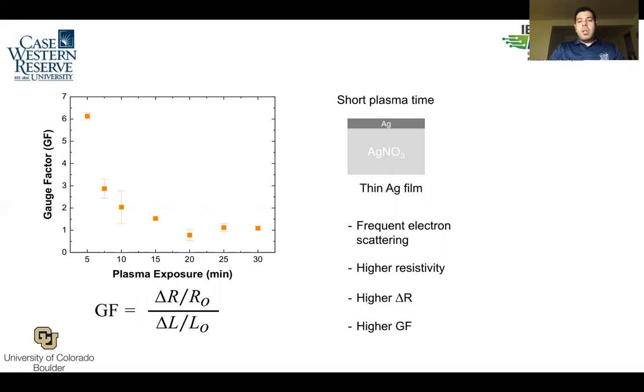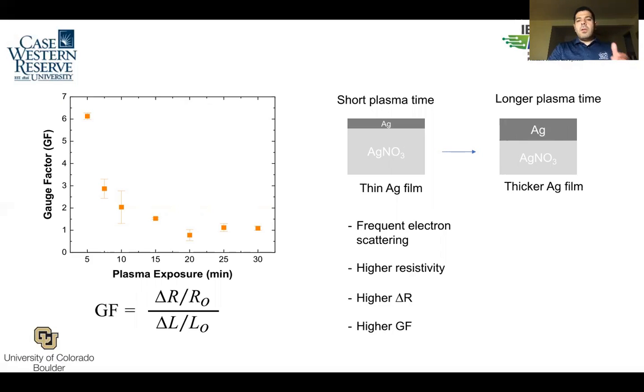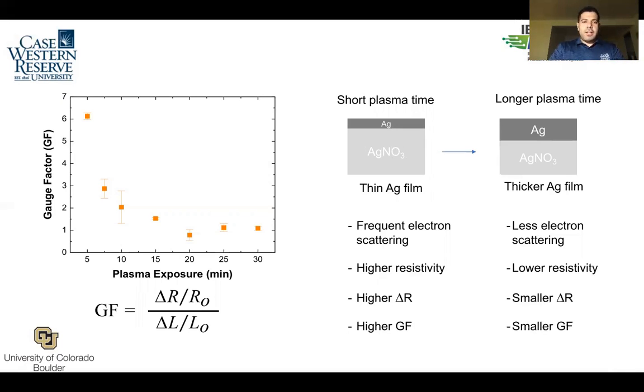gauge factor. For longer plasma exposure, you thicken the silver layer or film, which will reduce electron scattering, which means lower resistivity, lower delta R as you stretch the sample, and that translates into a smaller GF. So that's what we think is the science behind the decrease of the gauge factor.